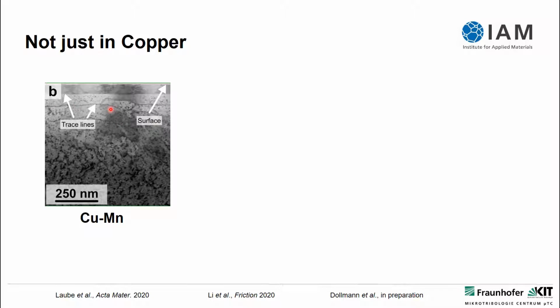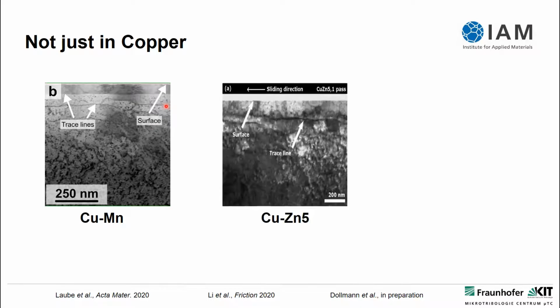And there we also see dislocation trace lines, actually several of them, but the trace line phenomenon is also there in copper manganese alloys. The same is true for copper zinc, in this case copper zinc 5, where we do see the dislocation trace line.